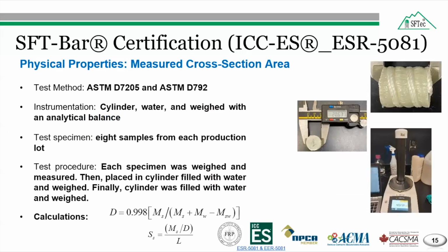So the volumetric method is used to measure the cross-sectional area, because the external surface coating of the GFRP bar doesn't allow an adequate cross-sectional area to be calculated. The specimens were tested in accordance with ASTM D7205 and ASTM D792. ASTM D792 is used to compute the specific gravity or density of the specimen. The instruments used in the test were a cylinder and a measuring scale. The specimens were weighed with an analytical balance to 1 milligram precision.